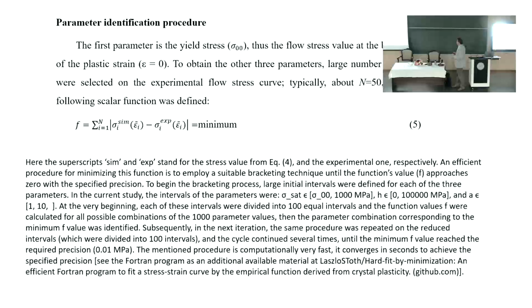So I take between 0 and let's say 1,000 megapascal. If it is aluminum, certainly it will be there. If it is a TRIP steel, perhaps I need to put 2,000. For the H, again, this is a rate of hardening, so I put up to 100,000 megapascal.